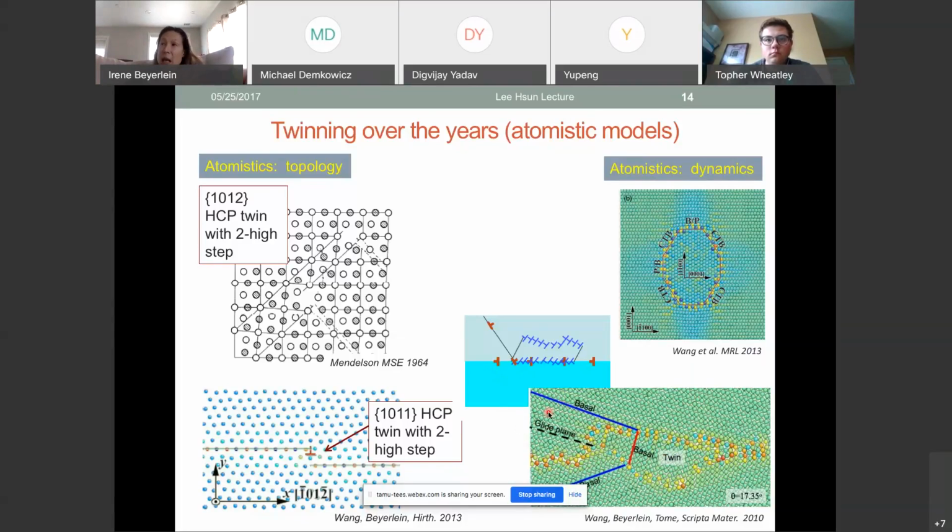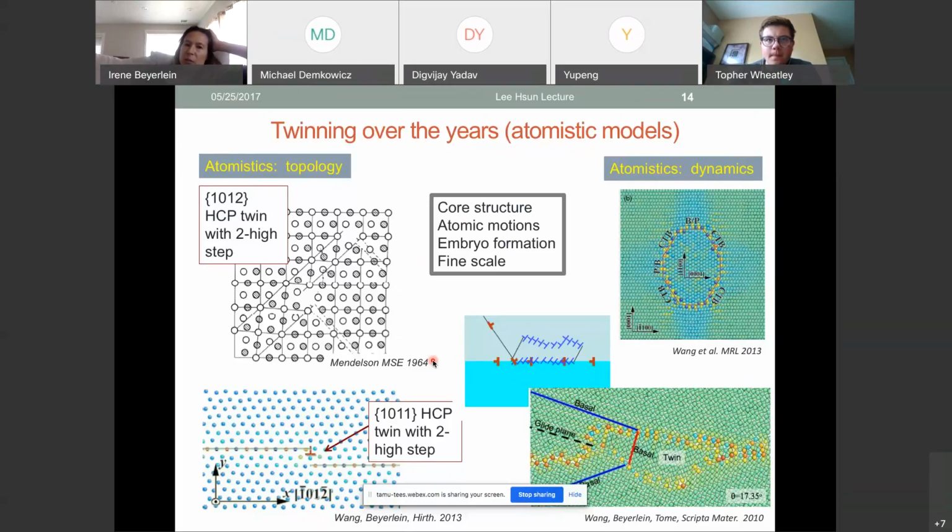under dynamics, under loading, and with a local stress field applied by, let's say, a pileup, that can cause a reaction of these stationary defects within the grain boundary to then disassociate and create a twin embryo. So atomistics has been very good with giving mechanisms by which twin nucleation would occur. And so that is something that we don't get from a lot of those.